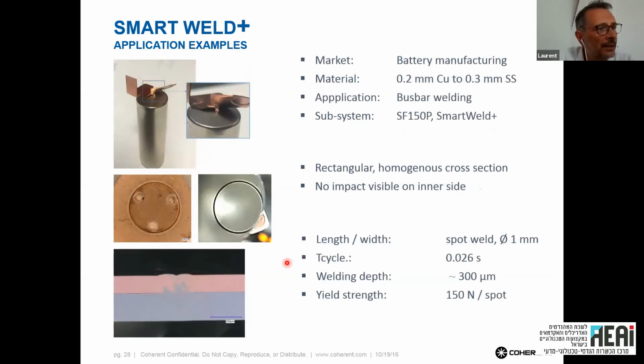Again, a battery. The main advantage in this case, it's the part and the laser is not moving. So it's more or less the same weld as the previous slide. But in this case, because we have a very, very small but enough working field, 20 millimeter by 20 millimeter, we are able to weld this circle with absolutely no movement from the battery or from the welding head. And for each spot size here, we use a specific pattern in order to have a spot around 1 millimeter diameter.